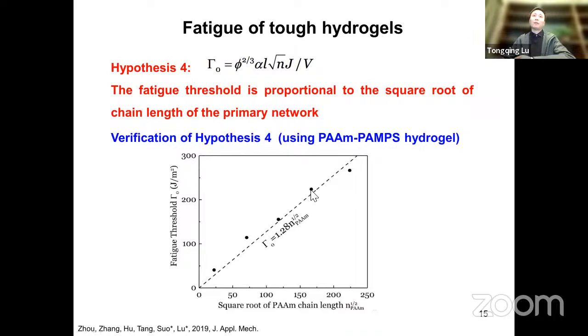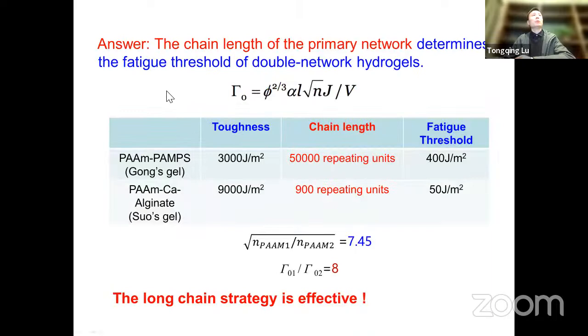So we have 5 kinds of hydrogels with different chain lengths, and we can see the result that this is square root of the chain length. This is fatigue threshold. So the prediction and the experimental result agree very well. So these two kinds of experiments verify that our hypothesis is correct. So now we can answer our question. So what determines the fatigue threshold? So actually the chain length of the primary network determines the fatigue threshold, and it follows this theoretical formula.